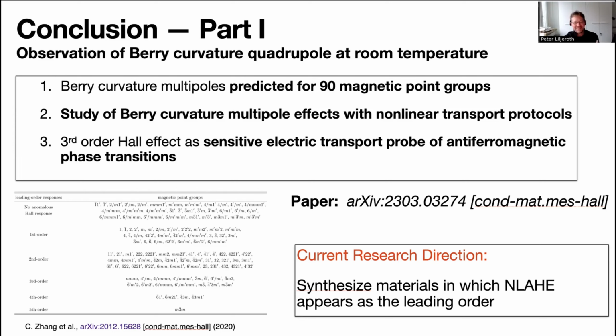Yeah, okay. Of course, going to the monolayer is everybody's dream, being an experimentalist or a transport person. No, the challenge, as a matter of fact, is really to realize thin film growth. Iron and tin like to stick together, but they don't like to stick to substrates. So growing these thin films from a kinetic viewpoint of synthesis in MBE is rather challenging. And for this reason, so far, we were not able to grow true Kagome thin films.